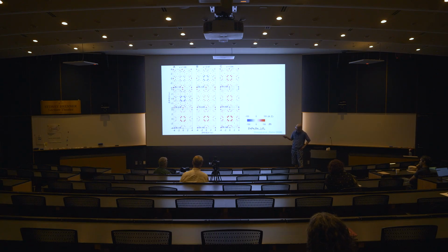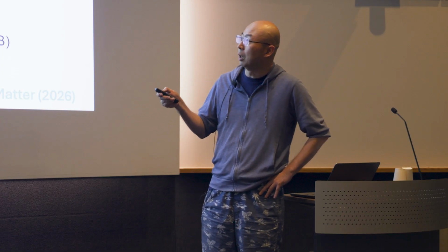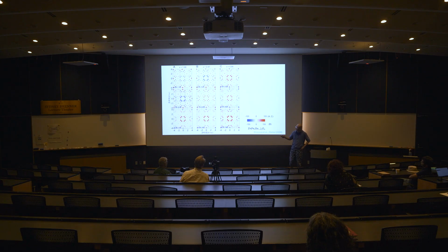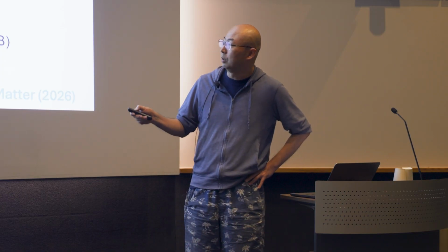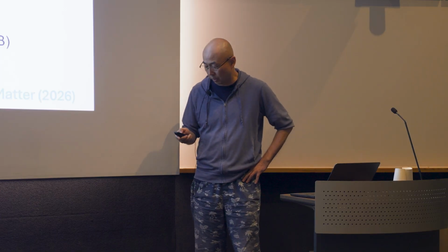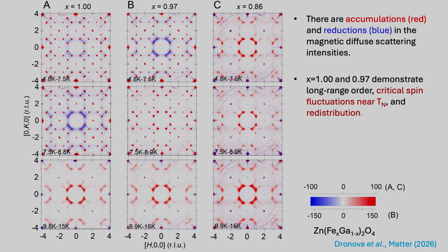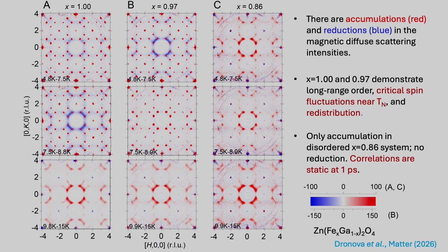However, if you go down to lower temperature, for the stoichiometric sample, we actually have redistribution of the spectral weight from this interstitial region to the Bragg peak. And this continues for all the subsequent low temperatures. For the disorder sample, however, this red accumulation of the spectral weight continues to the lowest temperature we have. So basically, there are two different types of behaviors. The first one, you can see spin fluctuations and the redistribution in the sample. And the second one, you just see a static correlation accumulating on this time scale of 1 picosecond.